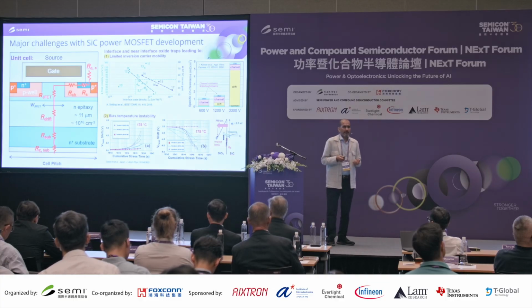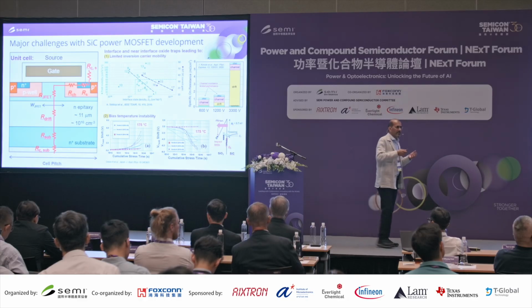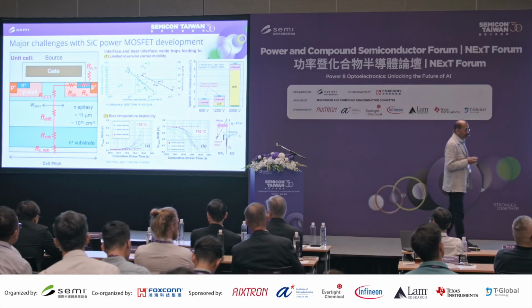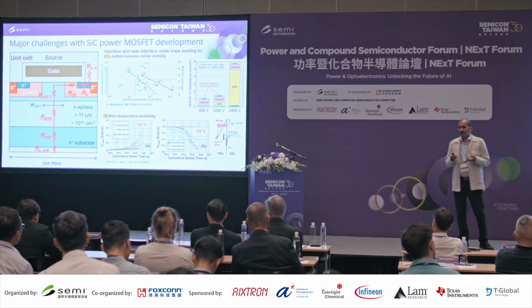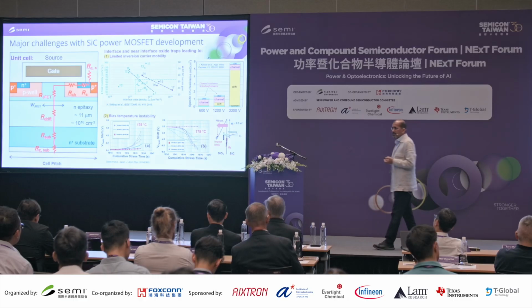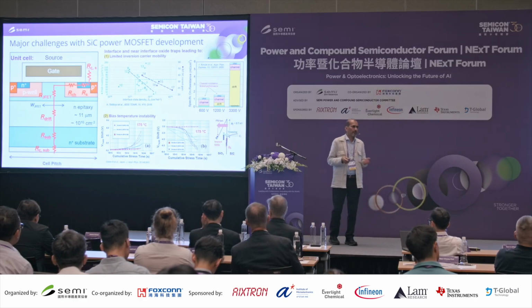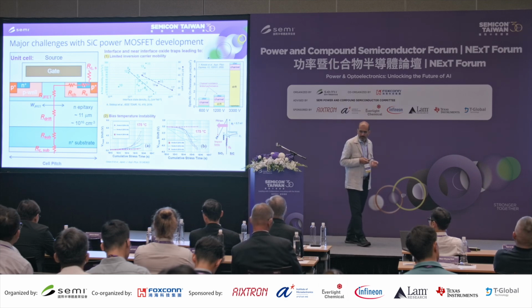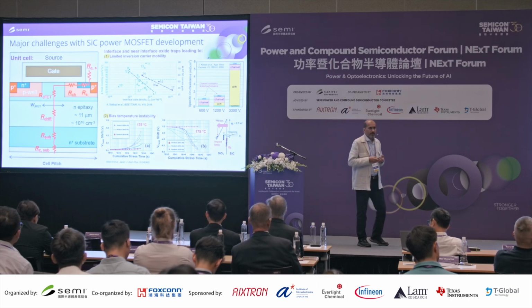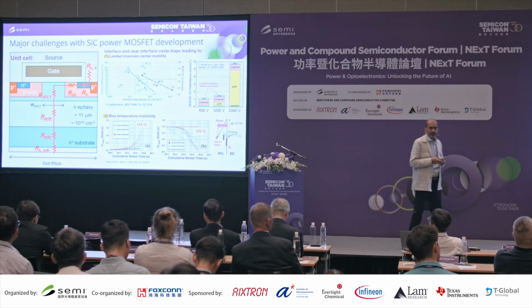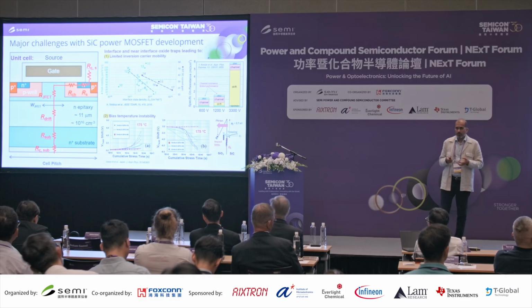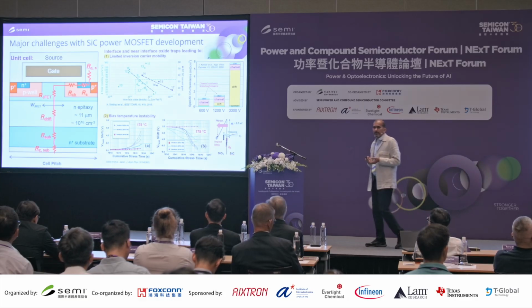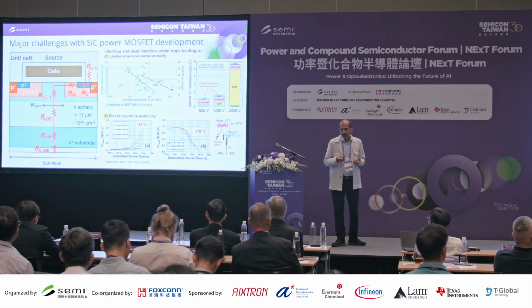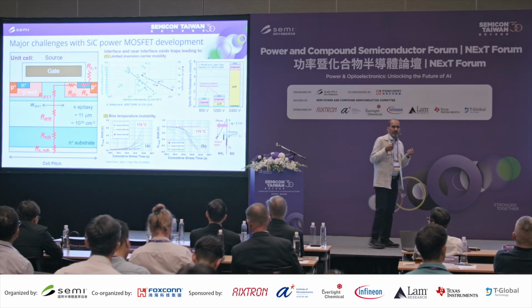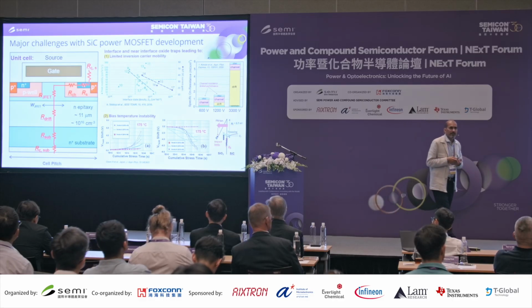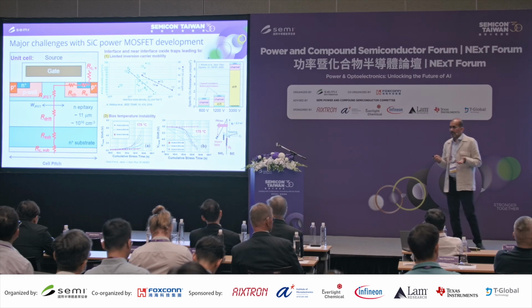To control that, people have optimized and utilized different kinds of post-oxidation anneal. People have used not only the grown oxide but also the deposited oxide, and annealed that in NO, N2O, N2 at different temperatures, to try to control these Dit values. And there is a very clear impact. You can see here the Dit impact on mobility. If you don't pay good attention, if you don't have the know-how, your channel mobility may be 10 to 15 centimeters squared per volt second, as bad as that, while the bulk mobility in silicon carbide is 1,000 plus. That's not the case with silicon.